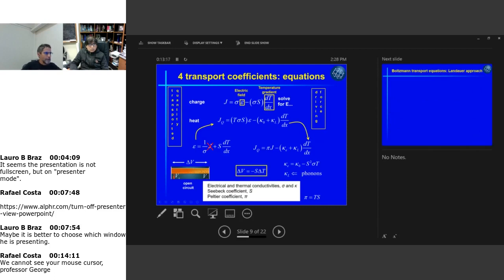So the Seebeck coefficient tells you how much voltage you get with a difference in temperature. And this comes straight out from this equation here. You can obviously do the opposite. You can say, well, I don't have any gradient of temperature. I have just a difference of potential, which was applied from the outside. In this case, dT/dx is going to be zero. Then you obtain that J is equal to sigma times the electric field, and sigma is your electrical conductivity.